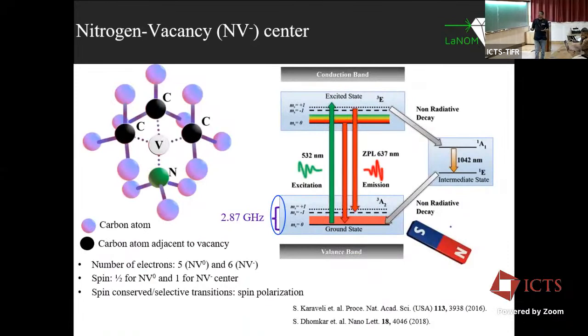So what is this NV center? We take a diamond lattice which is made of carbon atoms, and you have a nitrogen atom here which is externally placed, and near to that you have a vacancy, and this pair is known as the nitrogen vacancy center. Depending upon the electronic configuration, you have two charge states, NV0 and NV minus, and depending on that you have different spin states. One can optically excite these NV centers within the diamond lattice, and you can also manipulate the spin properties using microwave and magnetic fields.